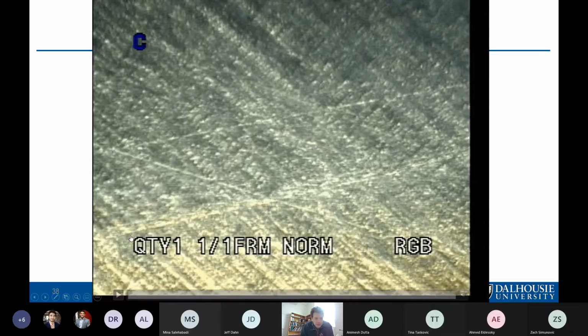This is a movie by Kevin Eberman at 3M Company. And this is looking down through electrolyte at a silicon tin amorphous thin film alloy with an optical microscope. Too bad there's no scale bar. I think this is a few millimeters width here. And there's a ring lithium counter electrode around this thing as a source of lithium ions.